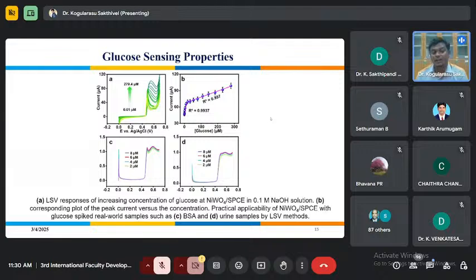Of course, it is very necessary because it must be increased gradually. Like when there is a sequential addition of glucose, the current must be increased gradually. There should not be any change in that sequence. So we have tested from 0.01 micromolar to 279.4 micromolar. Until that, there is no change in the sequential order, which means we can use this material to sense glucose in this linear range. So we can use it as a sensor to sense from 0.01 micromolar to 279.4 micromolar.